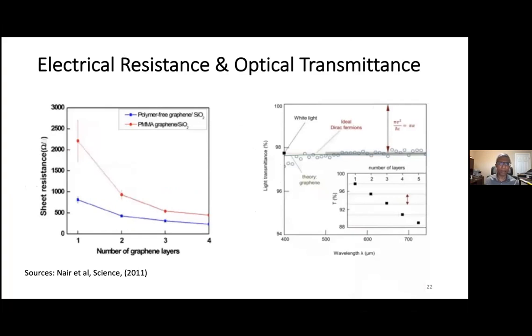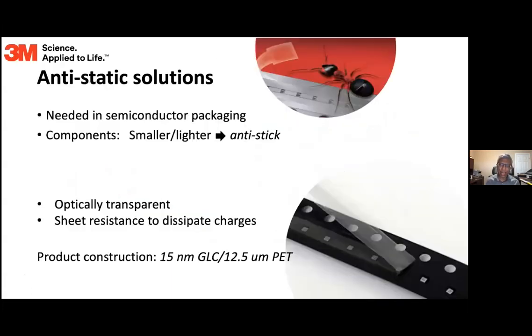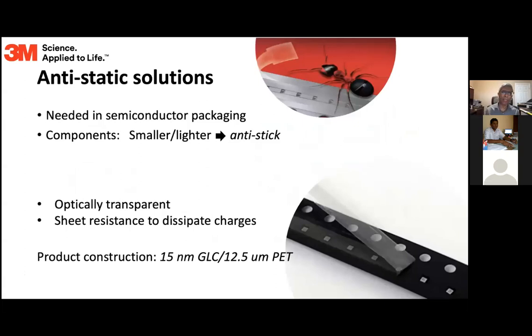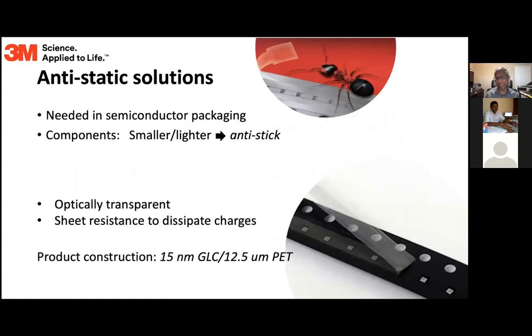Actually, let me talk about one more application, that is graphene's optical properties and electrical properties. When we have a single graphene layer, one atomic layer, the optical absorption is about 2.3%. When you stack more and more layers, it absorbs more, as you can imagine, which means the optical transmission gets lowered as well. At the same time, when we add many layers to make a multi-layer system, resistance also decreases. It becomes a better conductor. So now you have a tunability of these parameters. One application we developed using both properties is a solution for the semiconductor industry.